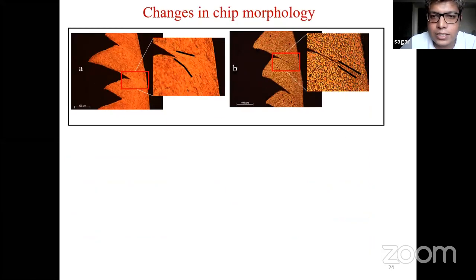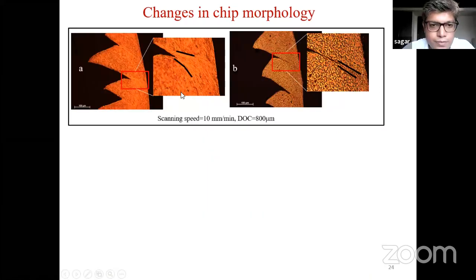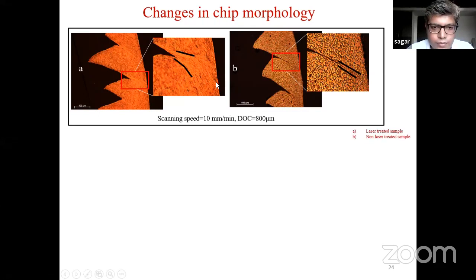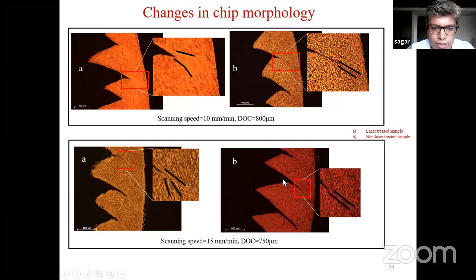So here you could see, let's see what exactly is happening in the shear band, and why this shear band is not getting localized. When you machine the non-laser treated samples, there is a localized shear band formation. Whereas in the laser treated samples, since the grain size is quite smaller and the hardness is quite higher in this region, there is a grain boundary strengthening effect. That means the localized plastic deformation has dispersed over the larger area, so that has reduced the force variation. So this is visible in every other case too.